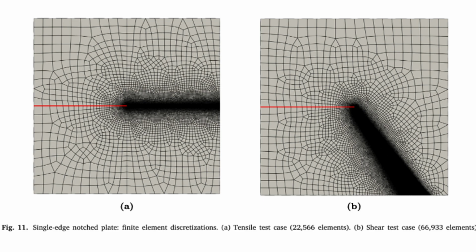Okay, this sounds great. In theory, modified L-BFGS for speed, gradient line search for stability, and even more speed. But does it actually work? Let's talk results. What did they test? They put it through its paces. They used 4 standard benchmark problems in fracture mechanics: a simple bar under tension, a single-edge notch plate under tension, SENPT, the same plate under shear, SENPS, and a symmetric 3-point bending test, S3PBT. Covering different kinds of loading and cracking behaviors.